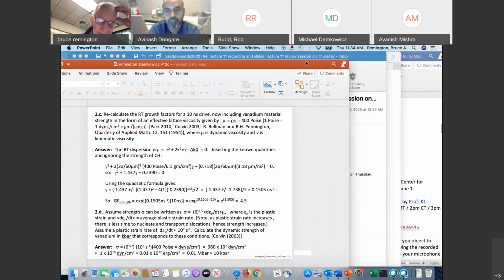And I think it was especially astonishing because lead was a case where there's extreme hardening, so that the strength at pressure is 250 times that at ambient conditions. And in a commentary, someone noted, this is like the Hulk of materials: in everyday ordinary conditions, it's kind of weak, not very impressive, but you agitate it and it becomes super strong.